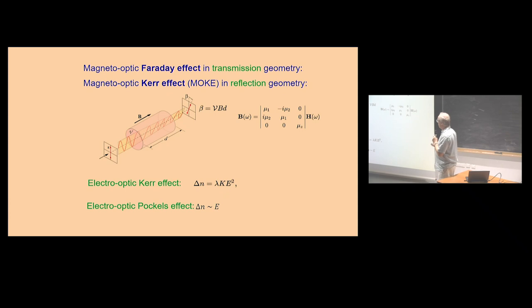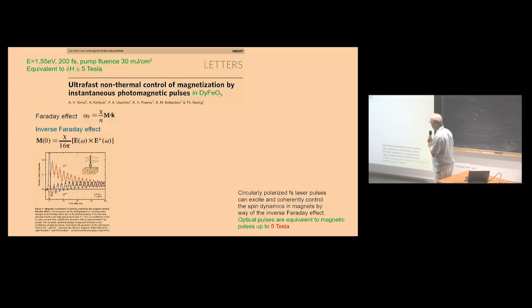In the case that you apply an electric field to the sample, you will observe a change of refractive index, birefringence, as we will see. This birefringence will be proportional to the electric field squared. So here it is linearly dependent on the magnetic field, and here it is square dependent on the electric field. Sometimes you can see birefringence linearly dependent on the electric field, but this is the so-called Pockels effect. The Pockels effect is allowed only in non-centrosymmetric systems, so in ferroelectrics. So let's go further. I mentioned that with an optical beam you can demagnetize a system if you heat the sample above the Curie temperature.